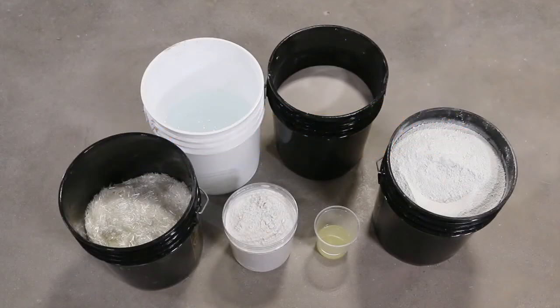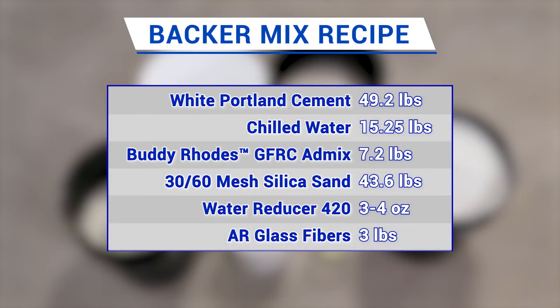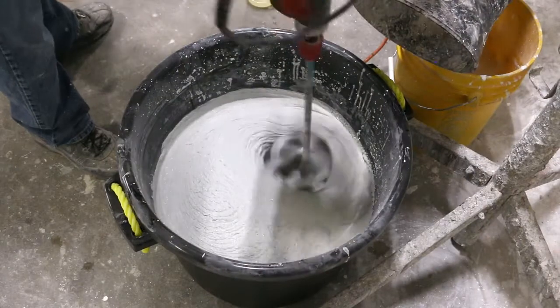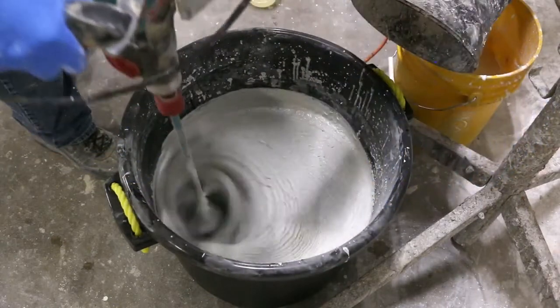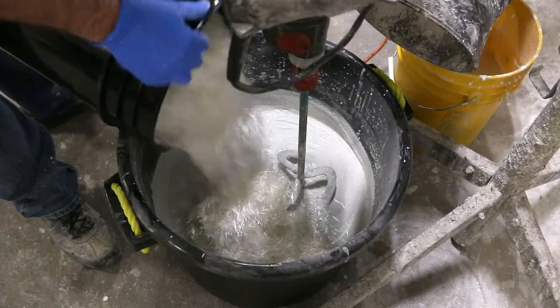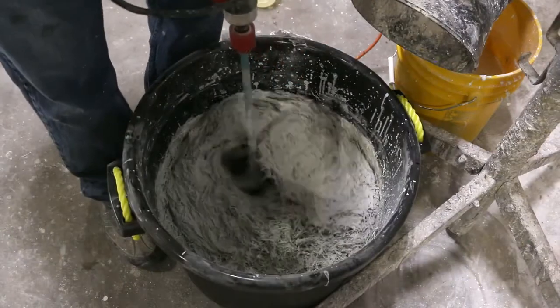For the backer mix, I used white Portland cement, chilled water, Buddy Rhodes GFRC admix, 30-60 mesh sand, water reducer 420, AR glass fibers. The backer mix was mixed the same as the face coat, mixing until fully blended, and added 3 lbs of AR glass fibers to the mix.